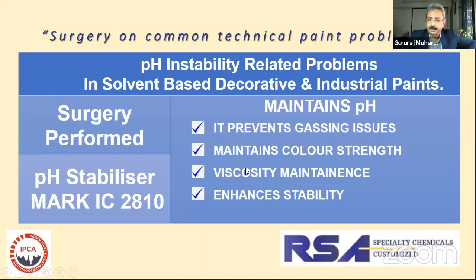So what is the remedy? As earlier, it's very simple. A pH stabilizer will vaccinate your paint against all these problems. Fortunately, if you're making both water-based and solvent-based paint, you don't have to maintain two inventories. The same pH stabilizer works in both the systems.